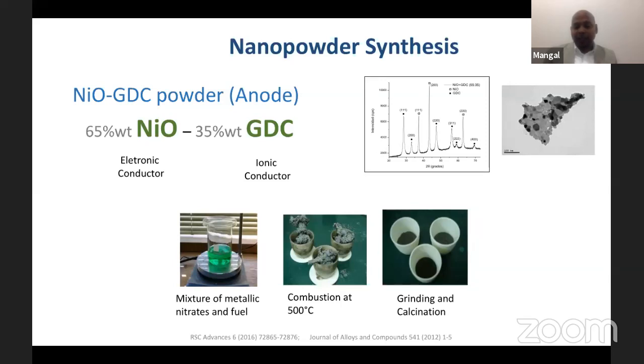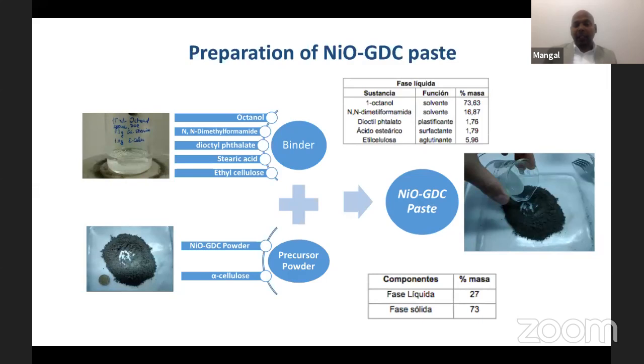It's a simple process of processing the powders, and finally we get the powders. These are nano-sized powders, and of course, we can have a spherical shape. When we have this kind of rapid synthesis, normally it is possible to obtain different, irregular morphology. But we can add some surface controlling agent to have the spherical nature of the powders. So after preparing these powders, we have to start preparing the paste. Because we have to fabricate the tube, we have to prepare the paste.